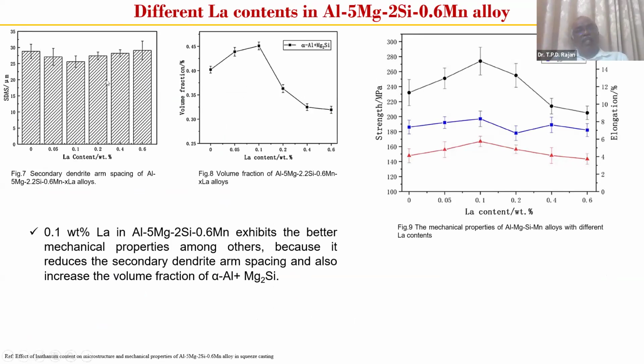Similarly, you take another element, lanthanum. With very minute quantities of lanthanum, 0.05, 0.1, 0.2, 0.4 or 0.6, you can see that the increase in lanthanum content enhances the mechanical properties through the reduction in the secondary dendritic arm spacing. That means it reduces the grain size, and this grain refinement enhances the mechanical properties. For example, as you increase the lanthanum content, the mechanical properties, especially the UTS, increase up to 0.1 percent. Beyond that, sometimes there is a coarsening of the precipitates. So we have to optimize the usage of lanthanum phases in the alloy, and an optimum volume fraction has to be used.